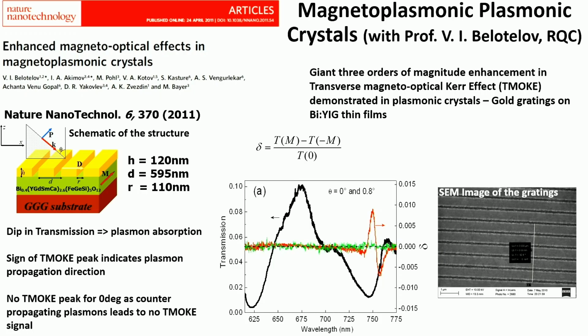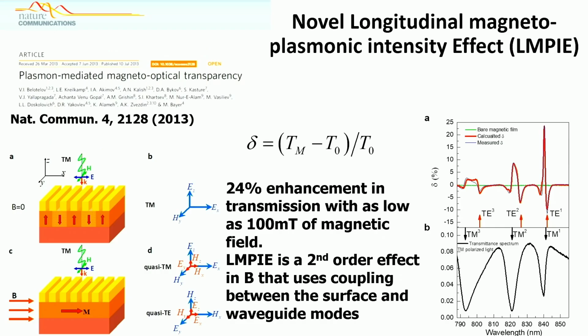So we showed that we can enhance the magneto-optical effects, both Kerr and Faraday effects, by up to 3 orders of magnitude. And not just in reflection, we can also see these in the transmission mode. Similarly, we demonstrated one novel longitudinal magnetoplasmonic intensity effect.